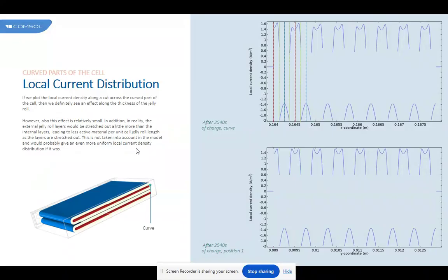Curved parts of the cell, local current distribution. If we plot the local current density along a cut across the curved part of the cell, then we definitely see an effect along the thickness of the jelly roll. However, this effect is also relatively small.